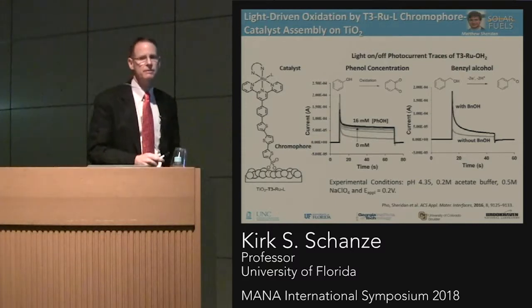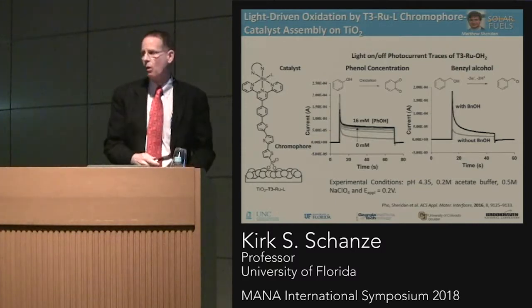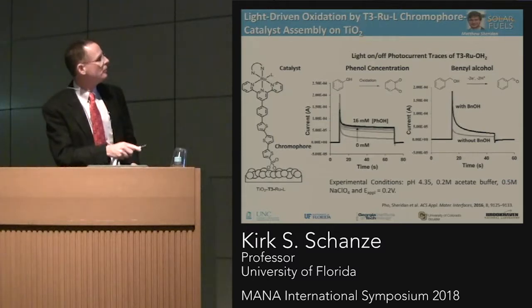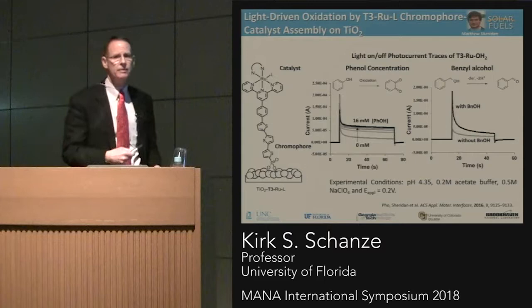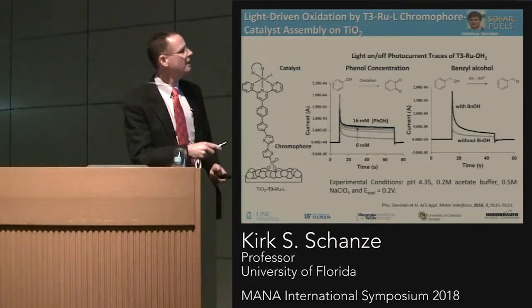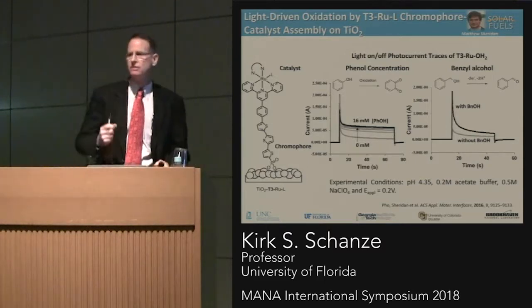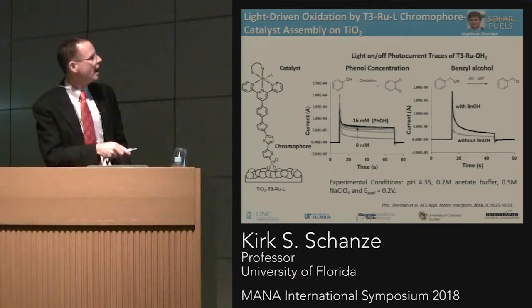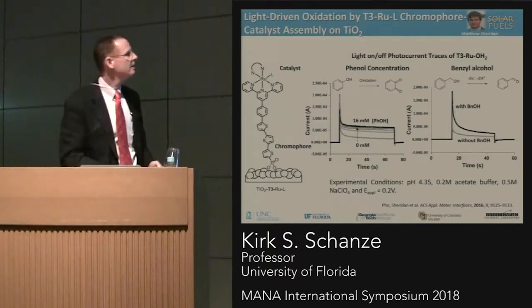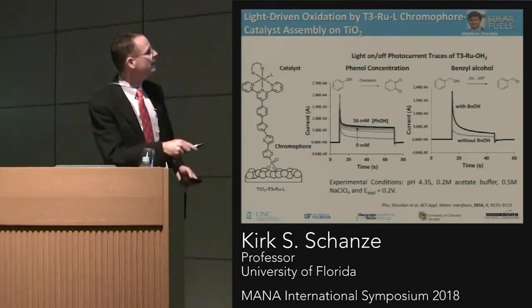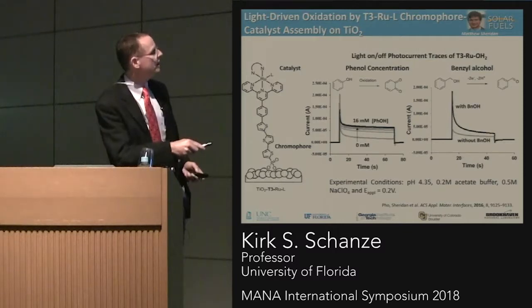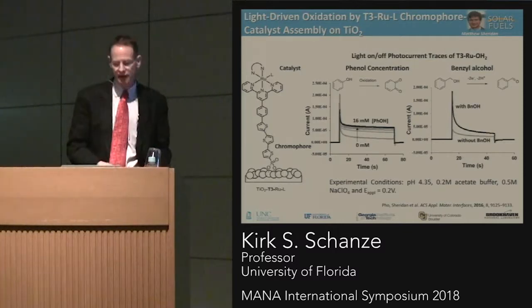Unfortunately, this particular assembly is not able to carry out water oxidation. The reason is that, as I mentioned previously, this catalyst has a rather low turnover frequency, and it's, in essence, too slow to compete with recombination of electrons coming back from the electrode, so this assembly can only carry out organic oxidations.